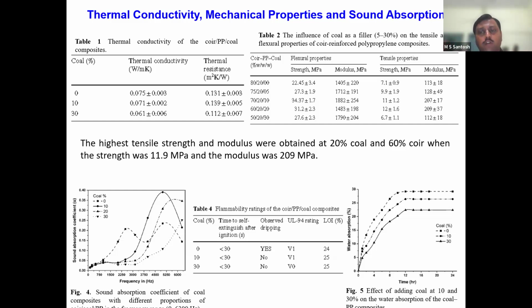When you look at the flexural and tensile properties, the variations in different compositions also clearly indicate that the 70-20-10 percentage of coir, polypropylene and coal shows better flexural strength and a higher modulus at the same 70-20-10 ratio. On the other hand, in terms of the tensile properties, the highest strength was seen at the 60-20-20 ratio, and the modulus was also highest at the same ratio, at 209.